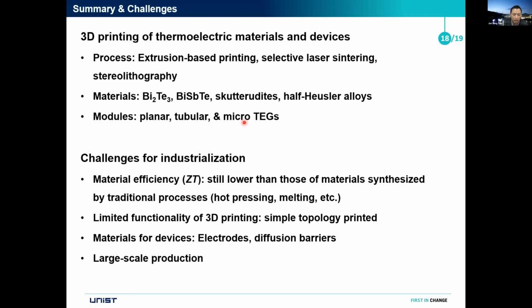Firstly, I think that we have to increase the material efficiency, the ZT value of the 3D printed thermoelectric material, because it is still lower than those of materials synthesized by traditional processes such as hot pressing and also melting methods, just 50% of the peak record high value.